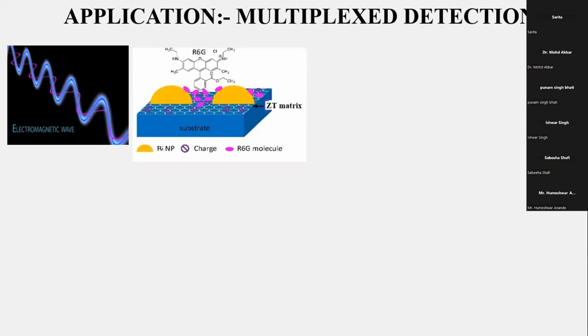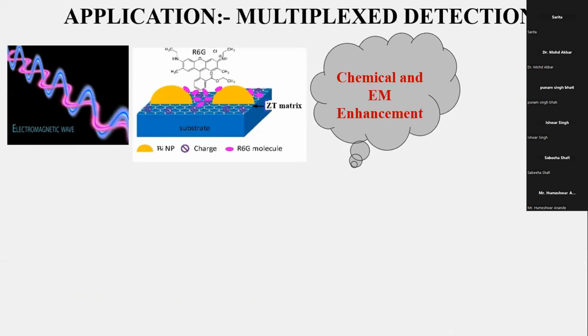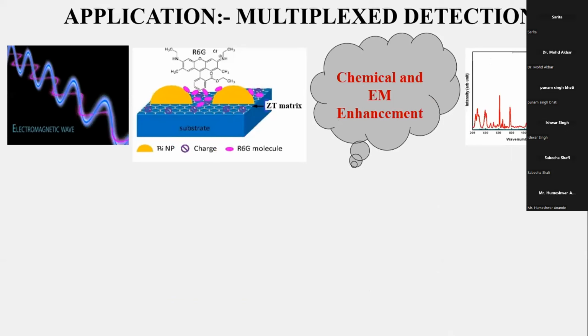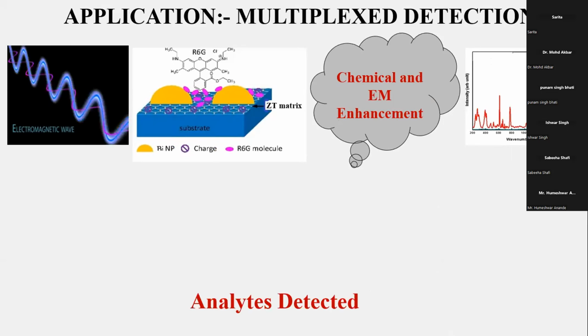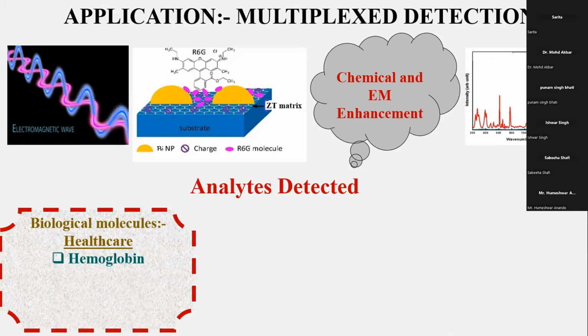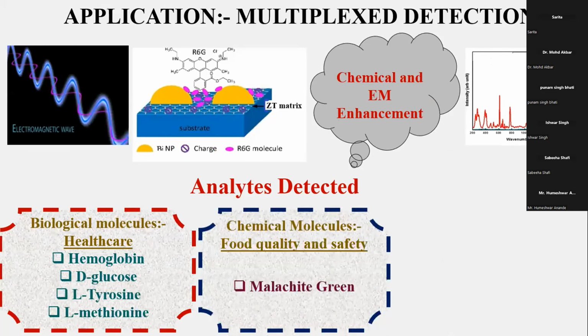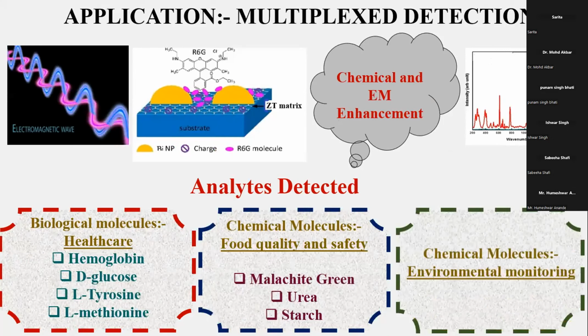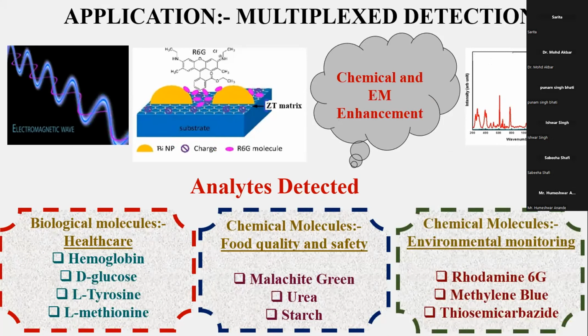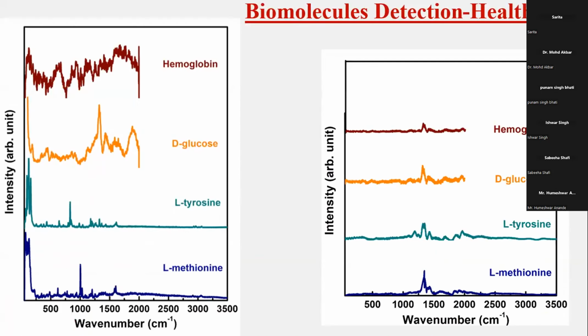It's nothing but an electromagnetic wave interacting with your matrix, and in which you are embedding a molecule through the chemical enhancement mechanism. You're getting the Raman signals. The analytes detected, I want to try in a multiplex detection range. So I have taken almost 9 molecules here: 4 of bio origin, hemoglobin, D-glucose, 2 amino acids, tyrosine and methionine, and chemical molecules for food quality and safety like malachite green, urea and starch, and chemical molecules for environmental monitoring, rhodamine 6G, methylene blue and thiocarbamide.